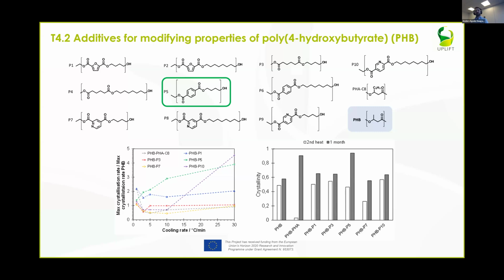An interesting aspect of these polyesters is that they have a drastic influence on the degree of crystallinity in the bacterial polyesters, but also that they affect the rate of crystallization, which is important if we consider applications in, for instance, injection molding and other processing techniques where we don't have a lot of time for crystallization to develop. This is extremely important if we want to tailor the properties of these materials and suppress some of the post-crystallization that is often present in PHA systems.